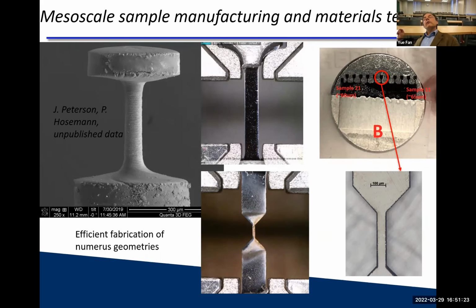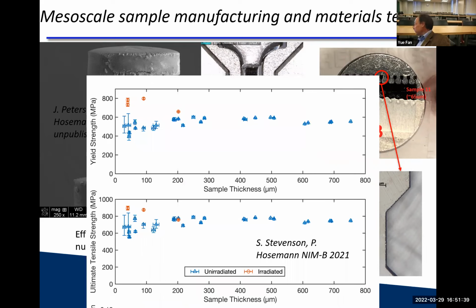And also we just did a test. I should have put that in, but we did EBSD of the surface as is. So you can actually get an EBSD signal of that without FIBbing if you get the parameters right. So with that, we are able to now test, for example, sample thickness versus yield strength, because we really want to know what that relationship looks like in the unirradiated case, and then irradiated. This is actually a 30 MeV deuteron, I think, irradiated sample.